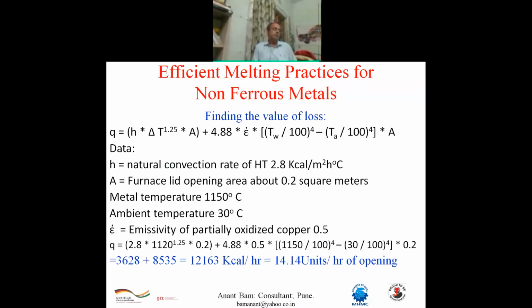If we observe your charging and melting cycle till the metal is ready for melting, then you can take it as a 60-40 ratio. 60% of the time the furnace has to remain open because someone is putting fresh material into it. Someone is performing metal treatment on it. But 40% of the time the furnace can be kept in closed condition under a cover, because that is the time between 2 charging cycles.